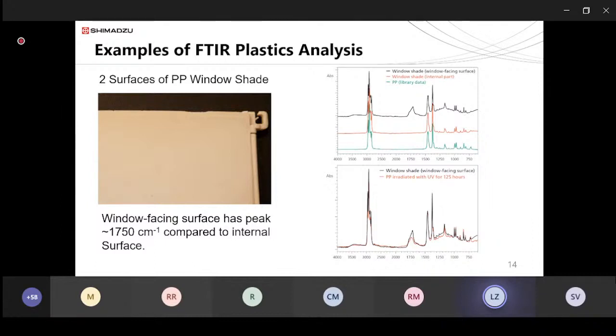So ideally, if we have a library that contains all the spectra for degraded plastics, we should be able to tell how degraded the plastic sample is. And in fact, Shimadzu has such a library. And on the lower right portion is our search result with the window-facing surface. And we can see that the window shade spectrum is matched to a PP sample that's irradiated with UV for 125 hours. So as you can see, FTIR can also be used to tell the degree of degradation of plastic samples if we have the appropriate libraries.